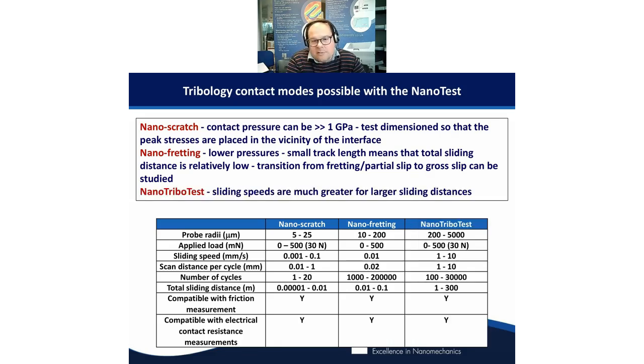And then we also have a thing called the NanoTriboTest, which is also a reciprocating technique, rather like fretting, but critically over a longer scan distance. So 1 to 10 millimeters would be typical. We can go longer than that, up to about 40 millimeters, in fact, but in most cases, there's no need to do so. Using the same type of load ranges and using larger tip radius probes. Okay, this again is more of a wear type test. It's essentially like a slightly scaled down, more conventional, traditional reciprocating tribometer test. And again, we measure friction as well as probe depth, and we can measure other secondary and tertiary signals as well, such as electrical contact resistance at the interface of the probe and the sample.